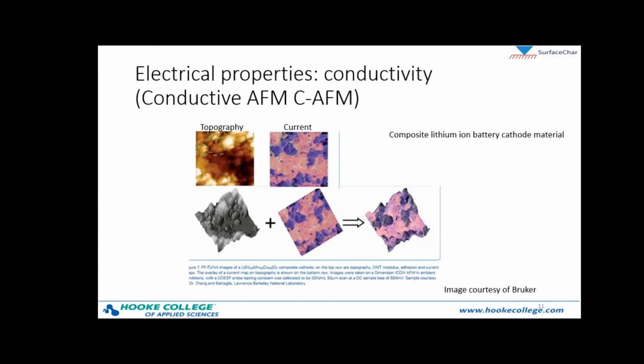You can also obtain a localized map of conductivity of your sample. In conductive AFM, the conductive tip is scanned in contact with the surface, while a voltage is applied between the tip and sample. This will generate an image of the current between the tip and sample. The example here shows a topography and current image of a lithium-ion battery cathode, which is a composite with multiple materials. Its different components can be assigned thanks to this mode.